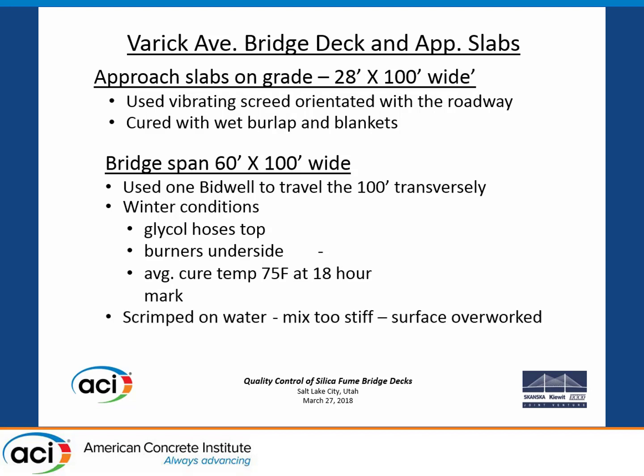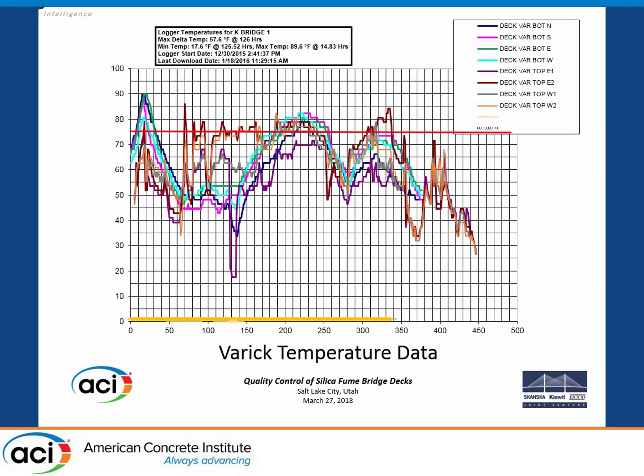We scrimped on the water because we wanted good concrete. And so the mix was too stiff, and it was overworked. We were late in applying the burlap. We were using wet burlap, and then we put blankets on top of that. And this is what we got for a heat profile. See about 75 degrees there the first 8 hours, and then they turn the heaters off, then they turn them back on. We owe the DOT 14 days cure on this, and it's going to be at least 45 degrees. We use 75 to get started. That's a lot more than 45 degrees.